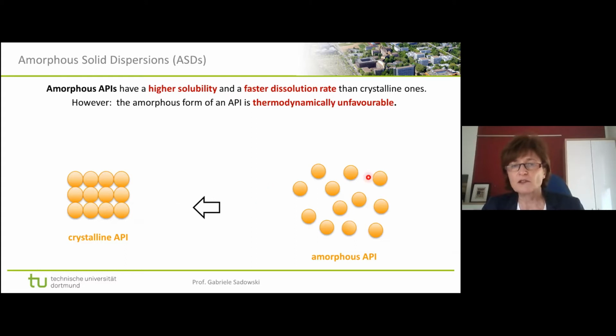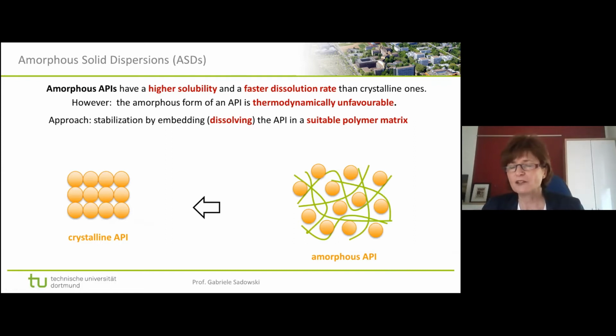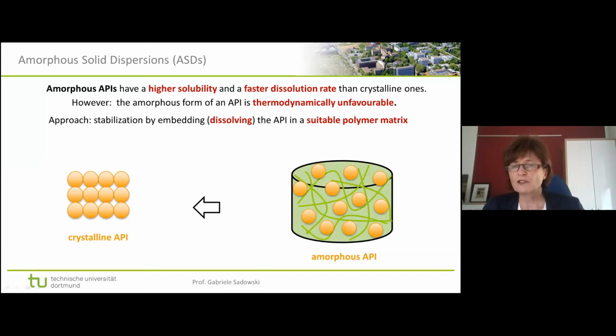So there is a way around it. What you need to do is stabilize the amorphous state of the API. One possibility to do that is to dissolve the API in a polymer matrix. Once you have it really thermodynamically dissolved, you have molecularly distinct API molecules. They do not form a lattice anymore because they are dissolved in the polymer. This is then, for example, available as a tablet, and this is what pharmacists call an amorphous solid dispersion.